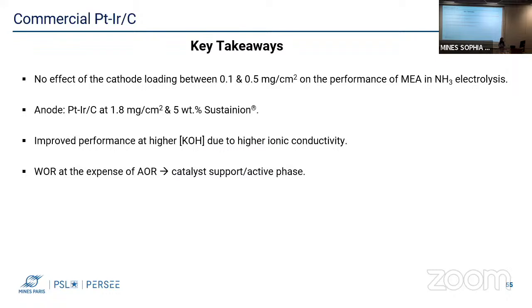At the end of this study, with the commercial catalyst, we could say that there was no effect of the cathode loading on the performance of the MEA between 0.1 and 0.5 milligram per centimeter square. The anode conditions that produced the best results include platinum iridium on carbon at a loading of 1.8 milligram per centimeter square and an ionomer weight percent of 5 weight percent.